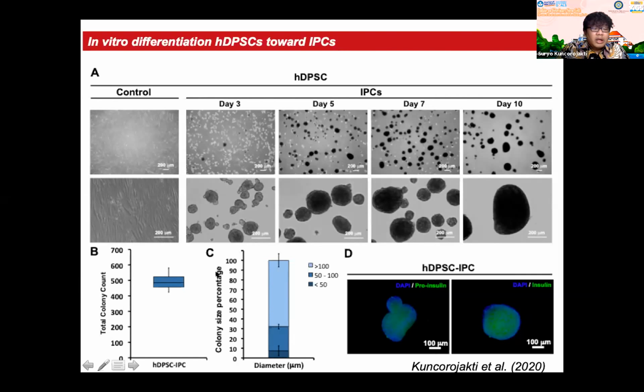The total colony count of cell aggregates obtained from this experiment was 424 to 581 colonies per batch, in which more than 70% of the cell aggregates had a diameter of more than 100 micrometers, while small colonies were not more than 10%. In addition, we also checked the cell aggregates with the immunocytochemistry method, and based on our study, the cell aggregates can express both pro-insulin and also insulin.